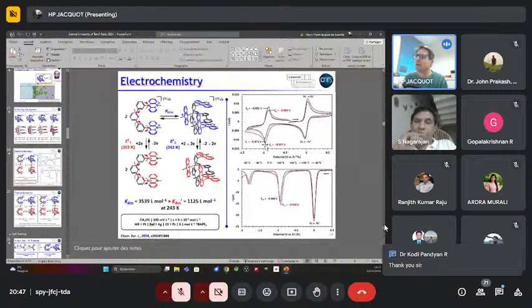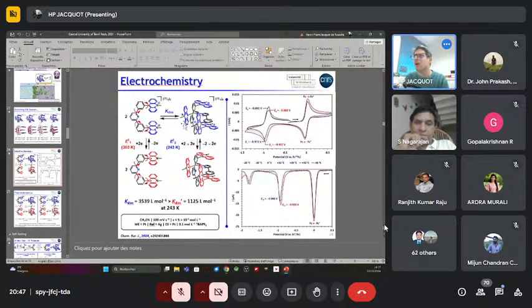And then the question we had is, what happens for the shift here? Could it come from a drift of the redox potential of just the acridinium unit itself, alone? So what we've done is that we looked at the model compound, just this 9-phenyl acridinium core, and we have just a very small shift of 3 millivolts. So the shift we see for the dimer comes from the dimer formation. We are sure of this. Of course, there were a lot of control experiments.